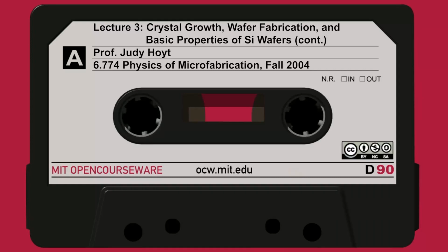So let's go on to slide 12. Here's a picture where I've actually filled in some numbers. People think they know these numbers. They're not known all that accurately, but it's believed that the double negatively charged V double minus level, a deep level, is about 0.1 eV below the conduction band. Similarly, it's believed that the V minus level is close to mid-gap, about 0.57 electron volts or so below the conduction band. People have done studies where they feel they can measure these numbers.